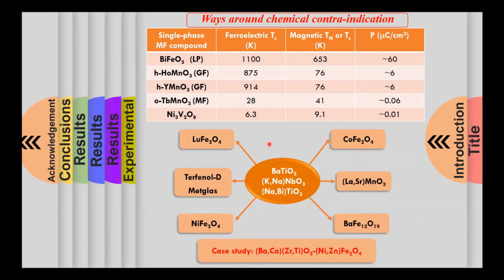And these are a few examples of some magnetic or magnetostrictive phases, like barium hexaferrite, cobalt ferrite, nickel ferrite, and some magnetic alloys like Terfenol-D and Metglas. We prepared composites of barium titanate with barium hexaferrite, as well as KNN with barium hexaferrite, using the solid state method and different wet chemical methods like sol-gel, co-precipitation and citrate combustion.